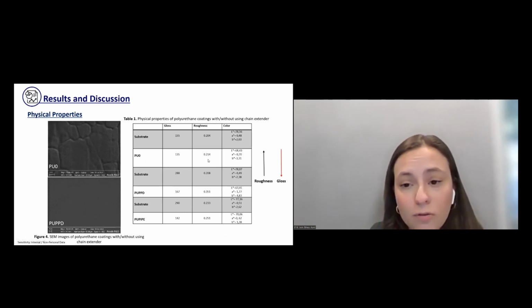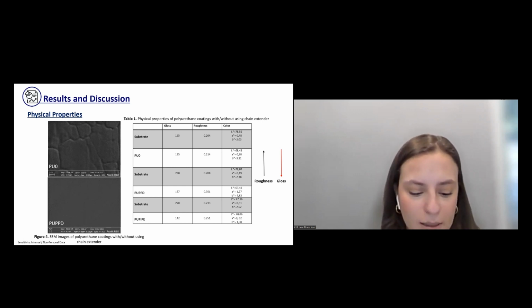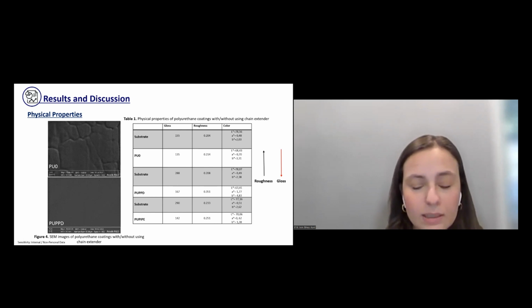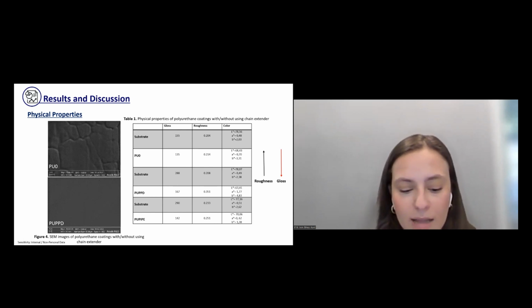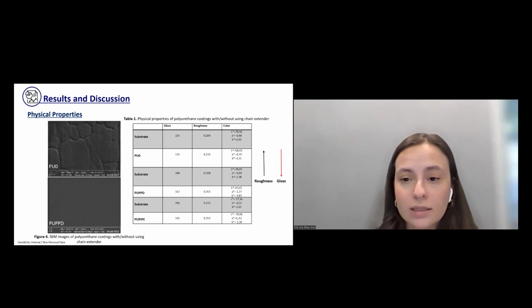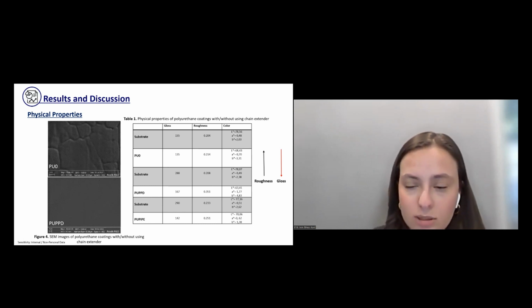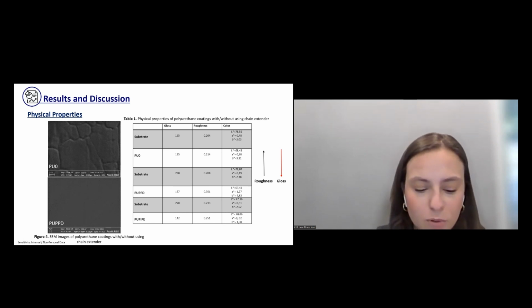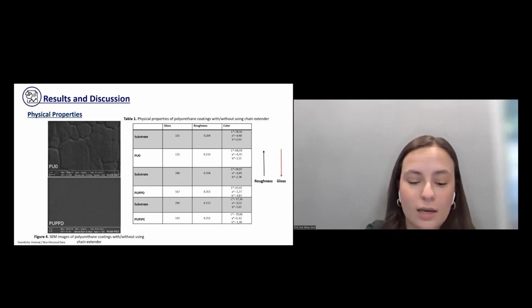An increased surface roughness of the coating causes diffused reflection of light, resulting in reduced gloss. We can see these results, but all the obtained values are high enough to classify the coatings as gloss coatings. And here in the table, the phenylenediamine chain extended sample has a darker color tone than the blank polyurethane sample. This may be because the blank polyurethane solution is a colorless, clear liquid, and the brownish color was attributed to the effect of the phenylenediamine chain extender.